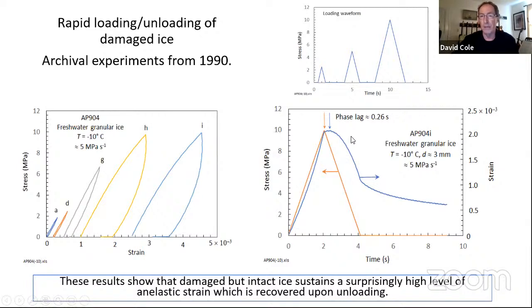So I was actually very surprised to see it. But it occurred to me in looking at these results that this would be the kind of mechanism that could possibly provide the strain energy that's needed to essentially effect negative damping, or provide a source of energy back into the structure from the ice. And so it's worth pursuing.